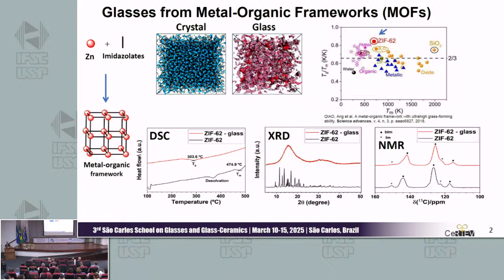In the first month of my PhD, I successfully obtained the glass from the system, as confirmed by DSC, XRD, and NMR. The next step of my research is to obtain composites of these glasses and luminescent MOFs. Thank you.